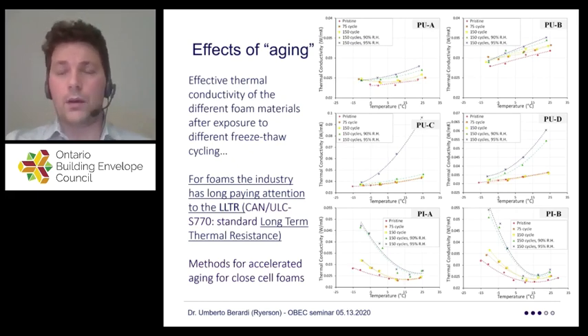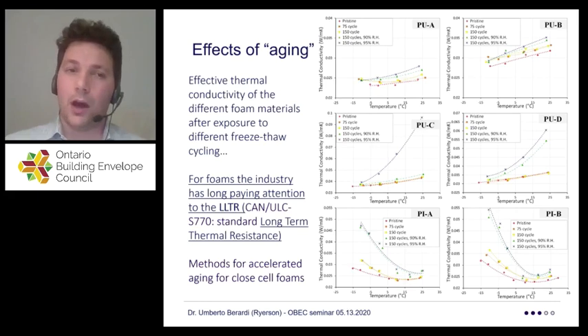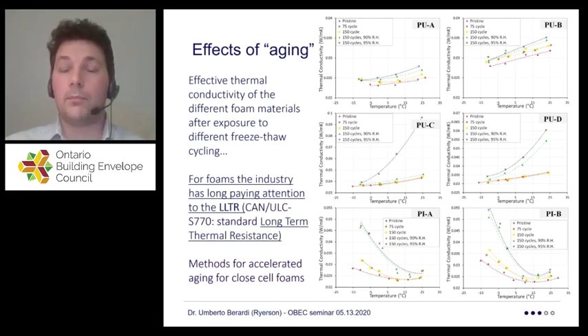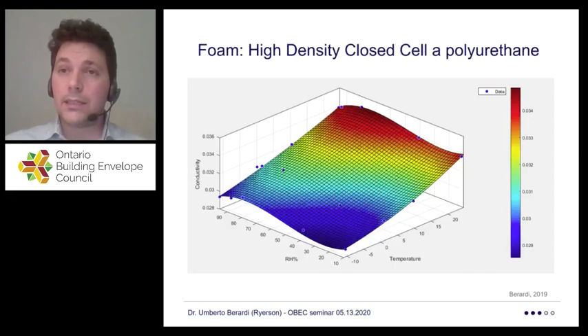We have also been testing products in terms of how the thermal conductivity of a material changes as the material ages. For people working a lot with foams, they may be aware that we have standards to look at the long-term thermal resistance. The foam industry doesn't like this approach because it forces the foam industry to look at long-term behaviors, versus a lot of other insulating companies. They only tell you the product behaviors when they're in the factory. They don't tell you what happens to fiberglass years after, or they don't really have any obligation to tell you those things. But the reality is, with time, a material tends to be more thermally conductive. I'm going to show you in a moment why that's the case.